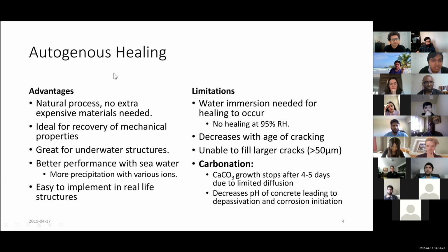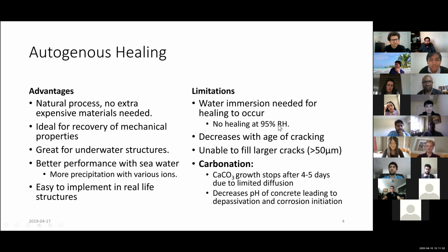In autogenous healing, there are some advantages, like it's less expensive and no extra expensive materials are needed. There is a limitation that water is needed most of the time for healing. Some studies have reported that even up to 95% relative humidity, there has been no healing of cracks. In terms of carbonation itself, it stops after 4 to 5 days, because in natural carbonation, carbon dioxide is not able to diffuse to the cracked locations and support healing. Also the pH of concrete decreases, which leads to depassivation of the protective film and initiation of corrosion. So these are the limitations as of now.